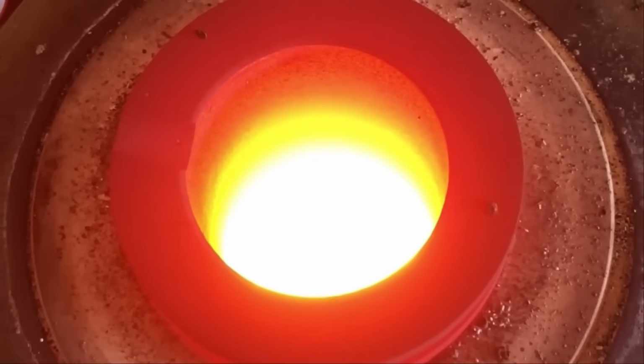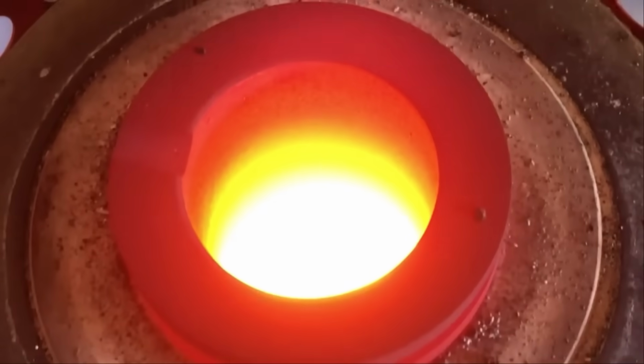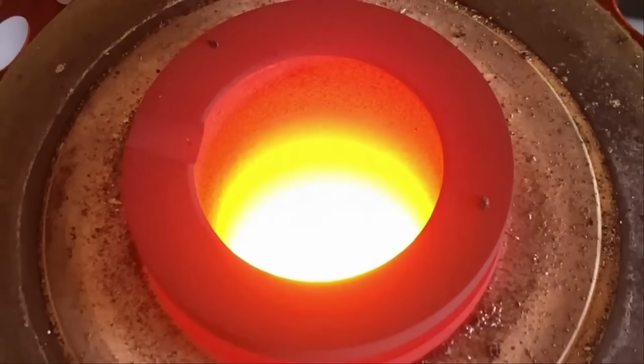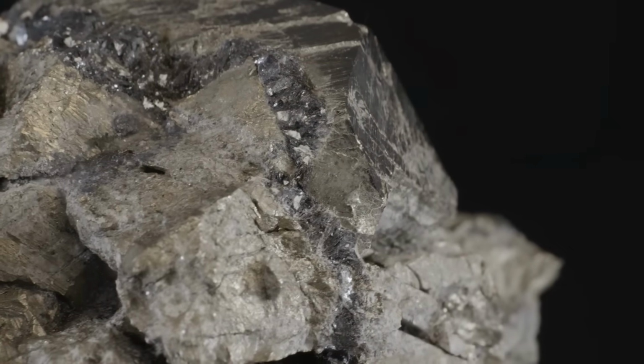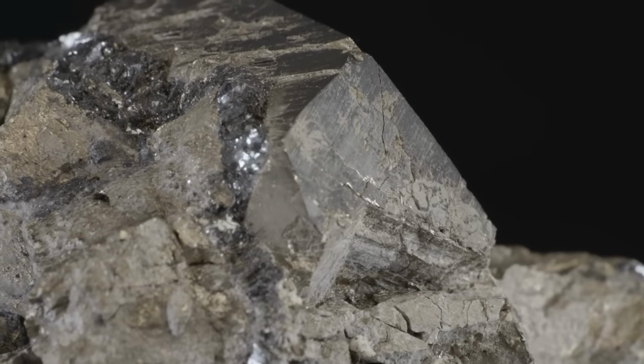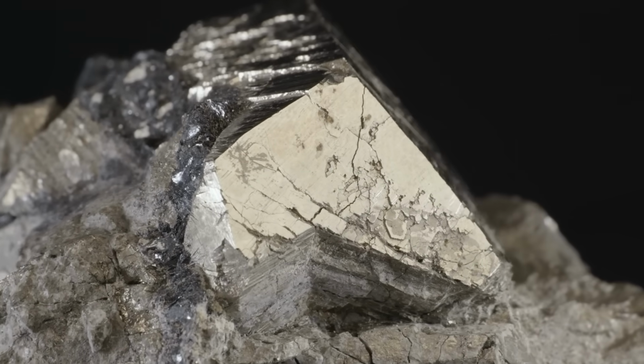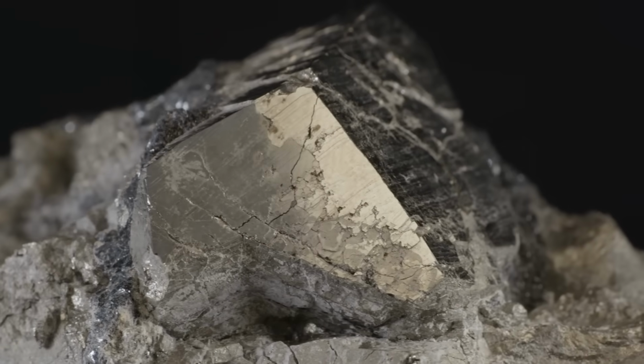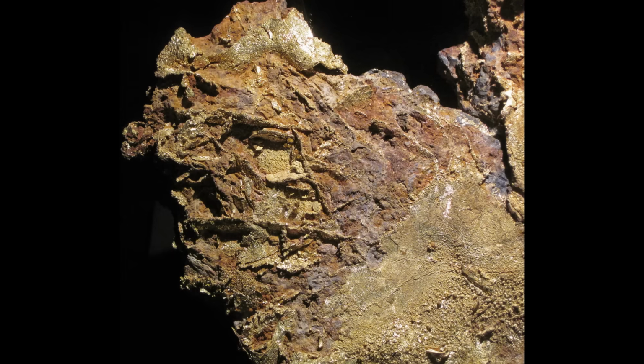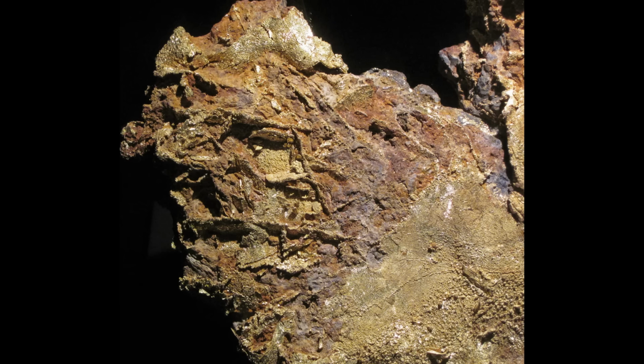Roasting is the most direct method. By heating sulfide-rich ore to high temperatures, typically above 500 to 700 degrees Celsius, you drive off sulfur gas and break down the mineral structure. Pyrite and arsenopyrite decompose, leaving behind iron oxides and freeing the gold inside. What you're doing is artificially creating an oxidation zone in a furnace. Done properly, it transforms invisible gold into material that can be recovered through gravity methods.